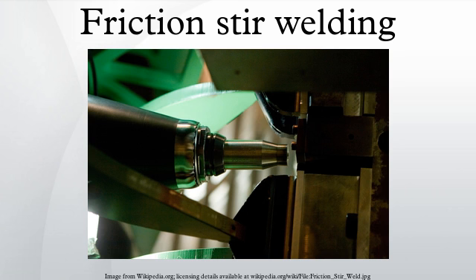It was noted that the copper entered the rotational zone around the pin, where it was broken up into fragments. These fragments were only found in the arc-shaped features of material behind the tool. The lighter material came from the retreating front side of the pin and was dragged around to the rear of the tool and filled in the gaps between the arcs of advancing side material. This material did not rotate around the pin, and the lower level of deformation resulted in a larger grain size. The primary advantage of this explanation is that it provides a plausible explanation for the production of the onion ring structure.